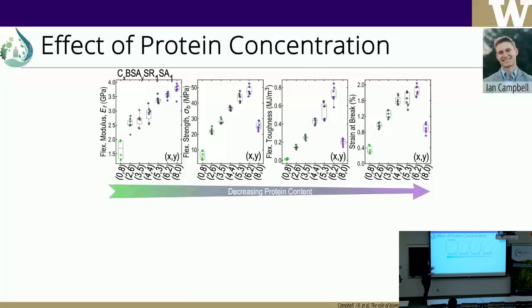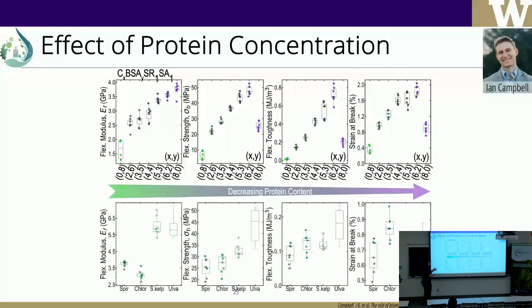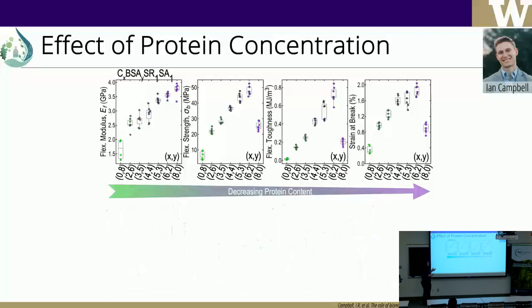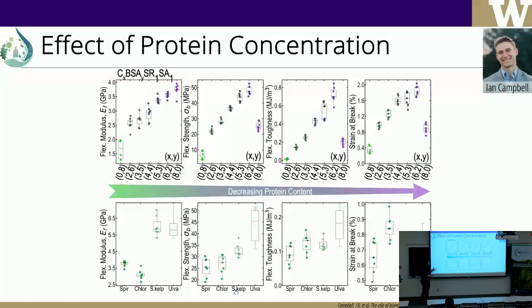Then we start decreasing protein content, and we start seeing that there are some compositions, in particular these two, where we have the smallest amount of protein mixed with cellulose, where we actually have some synergistic behavior. We are able to have higher strength than if we just had cellulose or protein. We are able to exceed that and be comparable in this case for the modulus. So primarily the strength is what is influenced, and it does make sense because even from a fiber composite point of view, you do need a matrix to transmit the load between your structural fibers, and you should be expecting to see the difference in the strength rather than the modulus. So even if this was not a natural composite, it would somehow make sense.